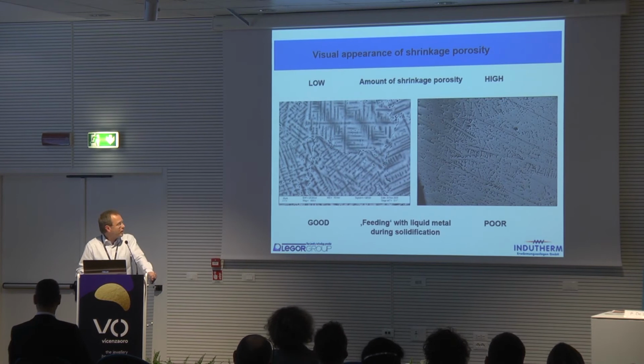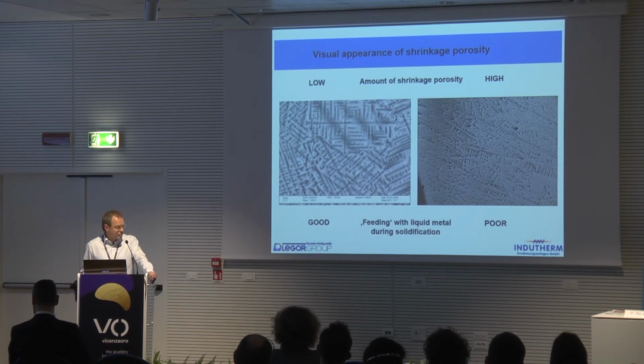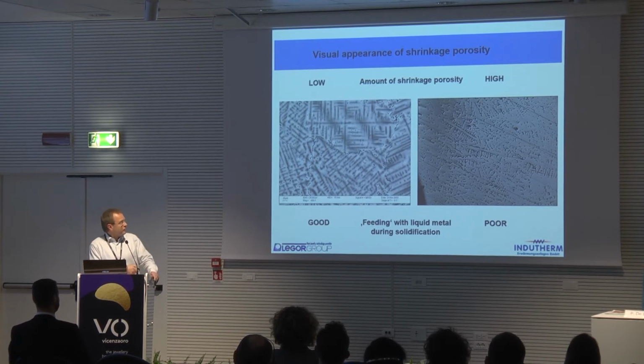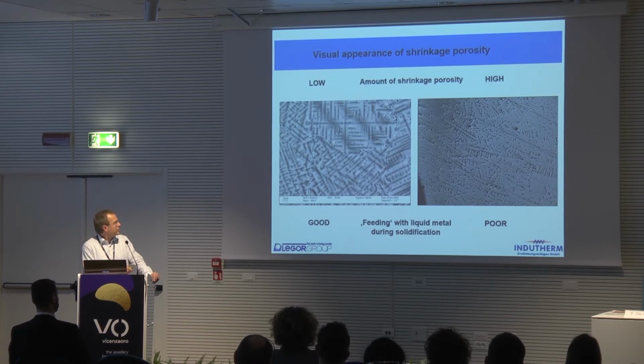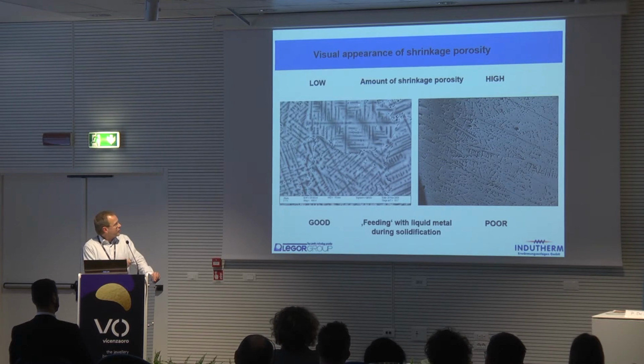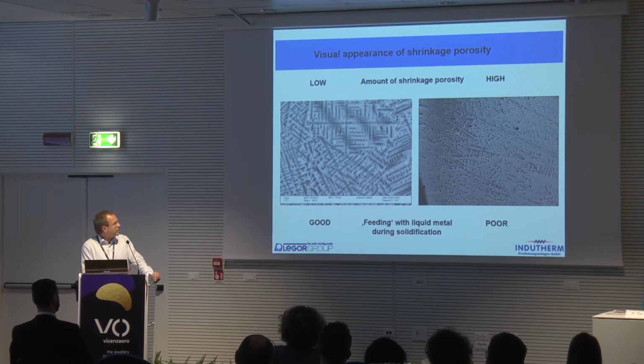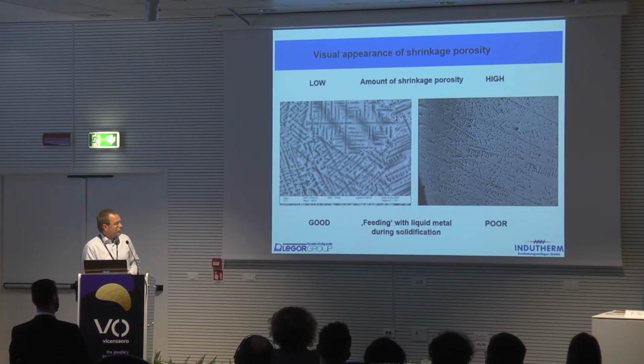But if this doesn't work well, as we can see on the right-hand side of the picture, I have a laser here, which is good. If this feeding of these voids doesn't work well, these voids will remain, and we have these typical irregular shaped pores, shrinkage pores. And on the left side, you see a micrograph where the microstructure has been etched. We can see also these crystals here. Yes, you can see some microvoids here, but all in all, the feeding went better than on the right side, and we can avoid shrinkage porosity.